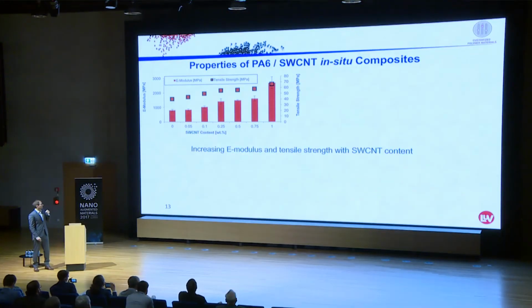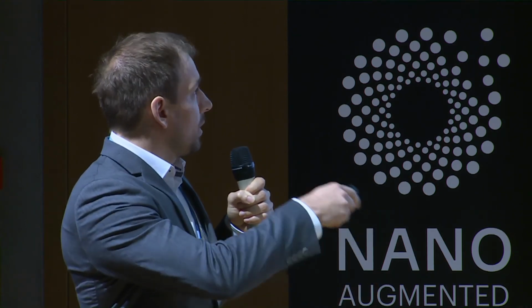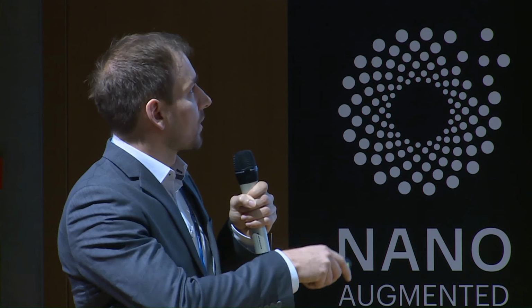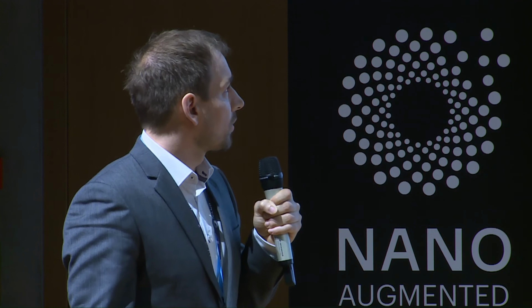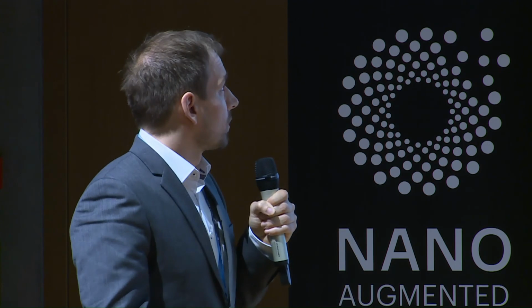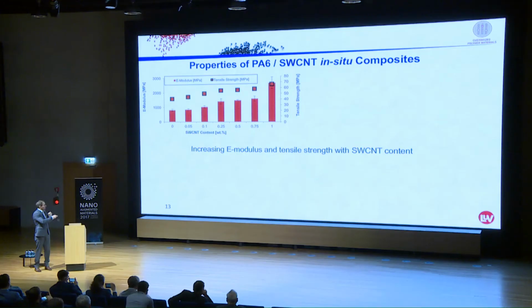All right, let's have a look at the mechanical properties of the in-situ made composites. We have here the filler content. I worked in concentrations from 0.05 to 1 weight%. On the left axis, we see the E modulus, on the right axis, the tensile strength. The bars are related to E modulus and the boxes to the tensile strength. We see an increase of both with the filler content. This is pretty much what we expected, but the effect is really strong. It's almost 3 times higher with 1% of TUBALLs.